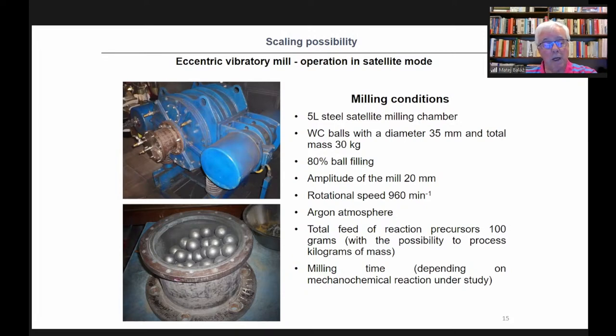It has a 5 liter inner volume. And you work with 80% of balls, tungsten carbide balls. We work with a diameter of 35 millimeters and total mass of 30 kilograms. And again, filling was 80%. And now the trick is that the movement and all science behind the big mill is the same as in the case of the satellite. If we work with the satellite mounted on this, of course, there is a need to work under protective atmosphere. You see these parts on the left side because it's very strong milling. So we obtain the same results.